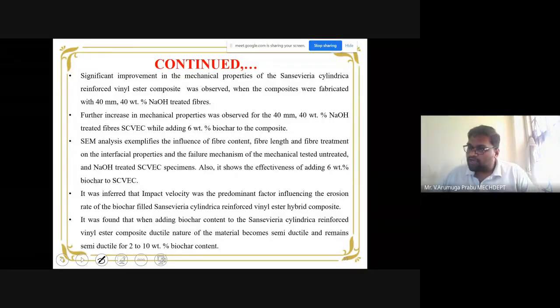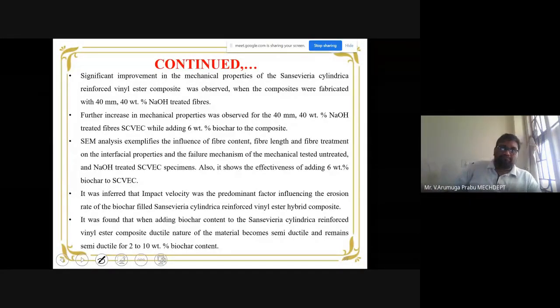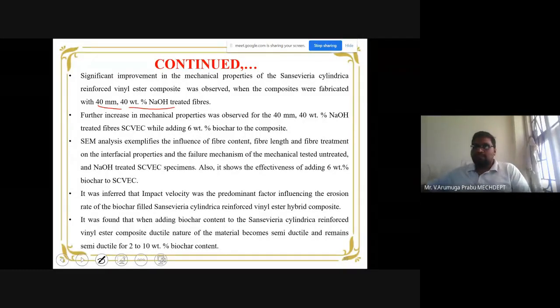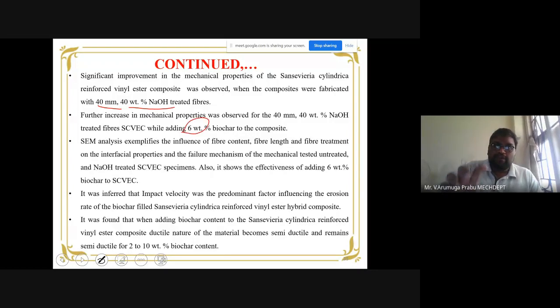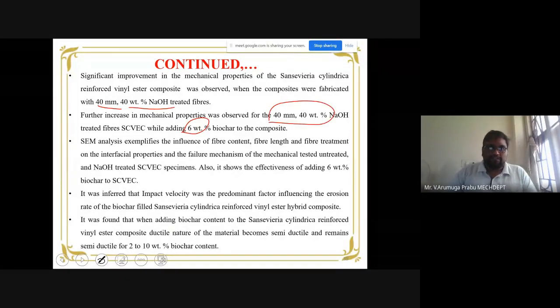Then the next one I would like to highlight in my summary is regarding the improvement. When we use biochar in the natural fiber, the better case where some good enhancement in the strength is noted is for 40 mm, 40 wt.% NaOH treated fibers. Okay, and in this case, 6 weight percentage of biochar along with the 40 mm, 40 wt.% NaOH treated fibers possesses better mechanical properties, where the influence of fiber content, fiber length, and fiber treatment on the properties was also noticed and analyzed in detail.